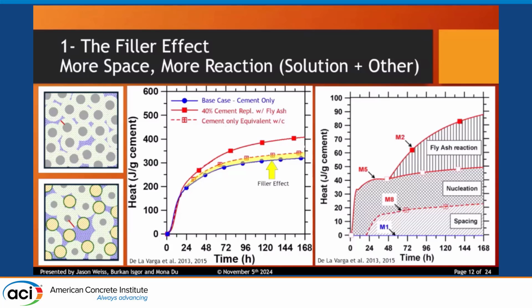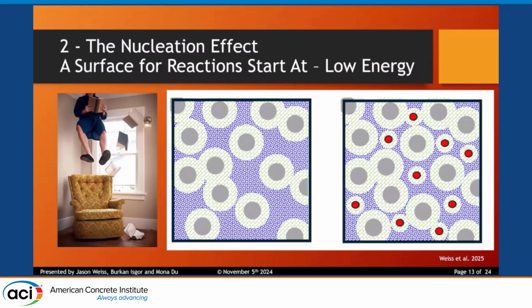So if we take a system with SCM in it, as I mentioned before, we're getting more of this hydration taking place. What we can actually do is use those heat curves. This heat curve is exactly like the one we saw in the previous presentation. The only difference is we integrated that rate of heat to get the total heat that's being released as a function of time. So if we looked at the system that was the cement only, with a filler, and then we started to look at the system where we now start to get other things in it, we can start to quantify the effects of each one of these different types of components that's happening in the system. We get a certain amount of hydration that's happening due to the filler effect, which is the spacing of the particles. It's a relatively small amount of heat, maybe 5% of the overall heat that's happening in the system. But it's a little bit delayed because it's not impacting the original spacing of the particles. It's really when those particles start to impinge. The second one is nucleation, which I'll talk about in a second. And then we actually get the fly ash itself reacting, whether it's reacting to form CSH or whether it's reacting to form the monocarbonates.